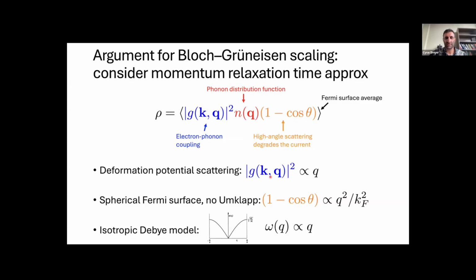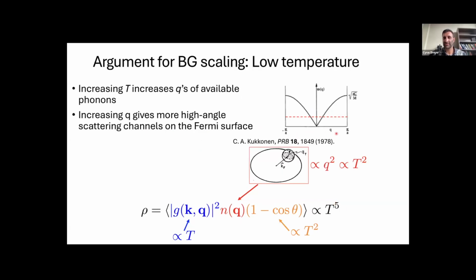And these elements have dependencies on, of course, the wave vector of the phonon. At low temperatures, when we basically have Debye phonons activated, all of the wave vector dependencies of these terms turn into temperature dependencies, because the higher the temperature, the larger the Q phonon we have for scattering. One of the key dependencies is this phonon distribution function, which basically depends on the intersection between the sphere of radius Q of the phonons available for scattering and the Fermi surface. For a small Q and a large Fermi surface, or in any case a spherical Fermi surface, the intersection goes like Q squared. It's a circle. That gives us a T squared. And when we combine it with the other temperature dependencies, we get T to the fifth.